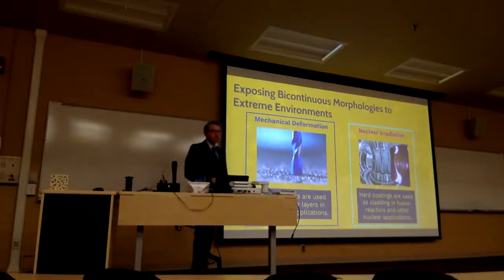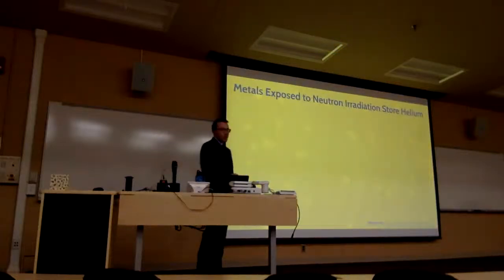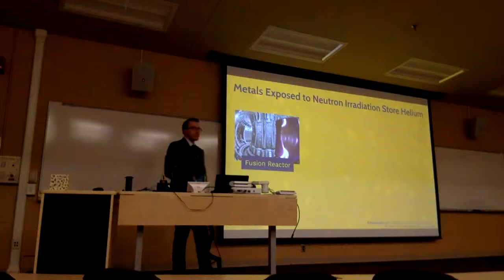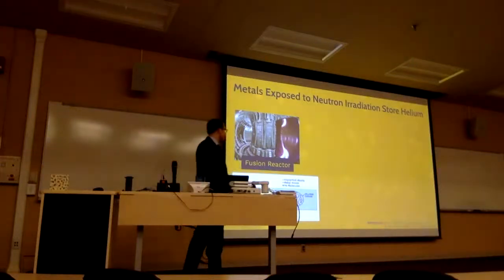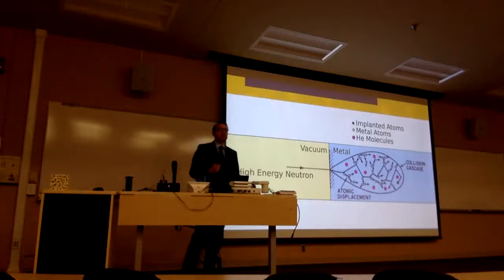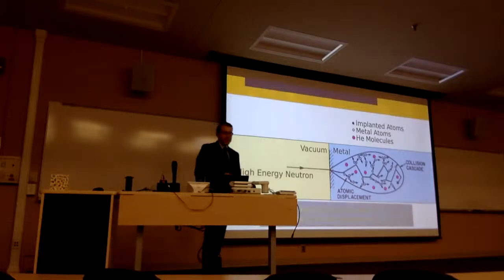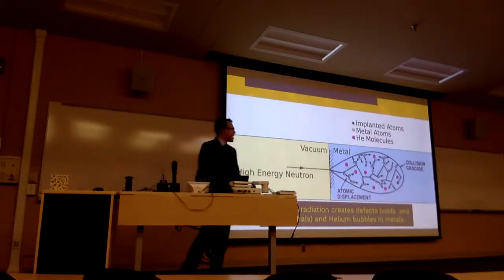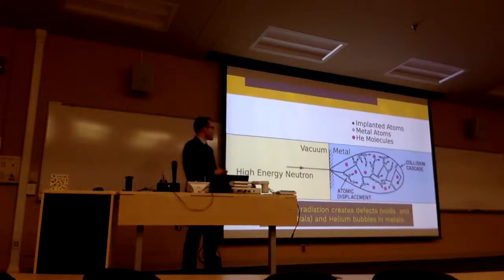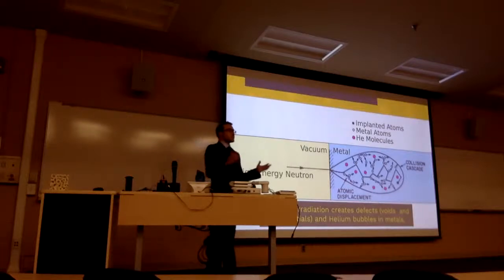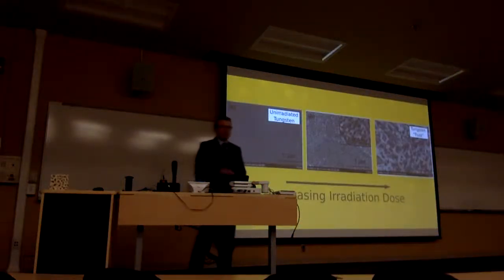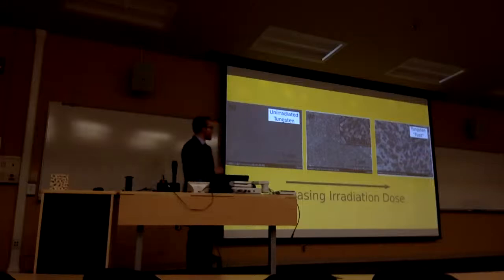Nuclear radiation is actually an important environment that uses thin films in the application. In neutron irradiation, such as in a fusion reactor, materials behave very interestingly: when they're struck by a high energy neutron, we actually have a cascade of damage that occurs inside of the material. We can have defects such as interstitials and voids, and the creation through nuclear transmutation of helium inside the metallic sample. Now, helium is completely insoluble with any metal. And so what happens is we start to develop porosity inside the sample as the irradiation dose increases.